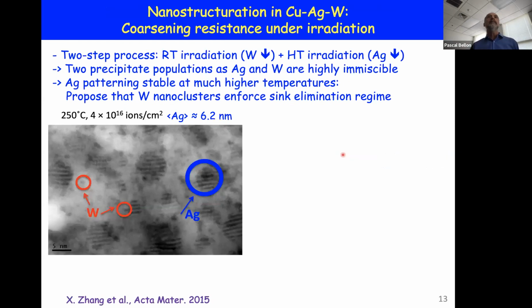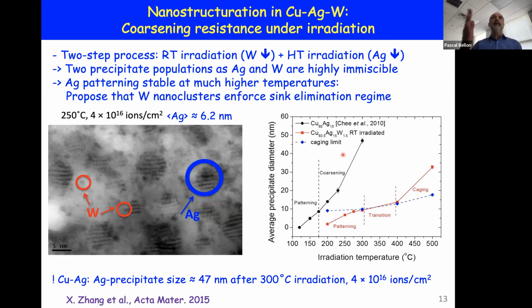temperature. So for instance, a benefit of this dual patterning is in an alloy where we combine both self-organization pathways, copper, silver, tungsten, we end up with 5 to 6 nanometer silver precipitates that coexist with 1 to 2 nanometer tungsten, very small clusters. And this material with a dual population of nanoprecipitates has an extreme resistance to radiation up to, say, 400 degrees Celsius. There are some details I'm not going to have time to discuss, but the point is that it's copper with small alloying additions, and that material has a nanostructure that is stable to about half of its melting temperature. So a high homologous temperature for this material suddenly.